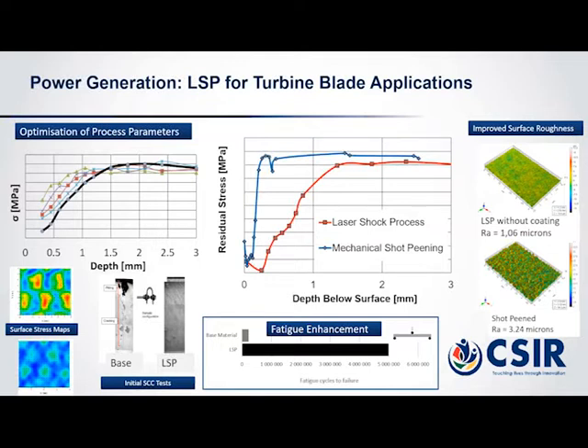For example, we have conducted simple three-point bending tests with multiple samples of the base material that only failed at a few 100,000 cycles. However, all laser peen samples actually reached over 5 million cycles and actually haven't failed, which is where we defined run out. In addition, initial U-bend stress corrosion cracking samples have also indicated promising results without failure of LSP over the defined testing period.